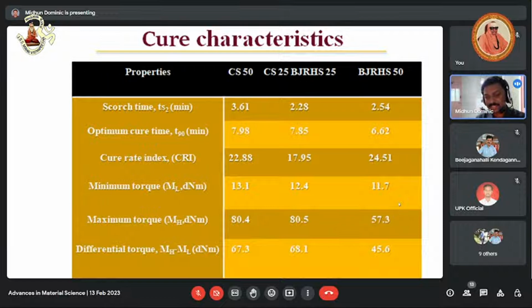But when we go through the results, we could see that that is not the case. Regarding the cure characteristics, next we will discuss some of the important properties of rubber compounding. The optimum cure time is the time required for 90% vulcanization. For commercial silica it takes around 7.98 minutes, and for BJRHS it is 6.02 minutes. So if you replace commercial silica with BJRHS, the cure time can be decreased. So that is an energy saving.